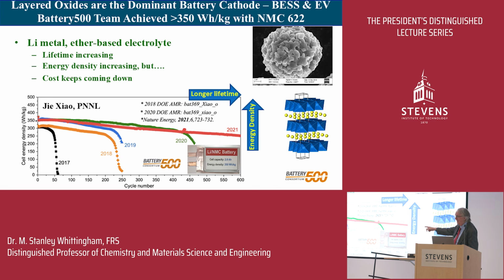This is our first 5 years of this program. In year 1, 2017, we could recharge this material 50 times and get 300 watt-hours per kilogram. Remember, commercial was 250. A year later, we got up to 250 cycles, so we said, let's increase the energy density, push it harder. So we got up to 350 in 2019, and today we're up to about 1,000 cycles at 350. So we can increase the energy density of these materials.